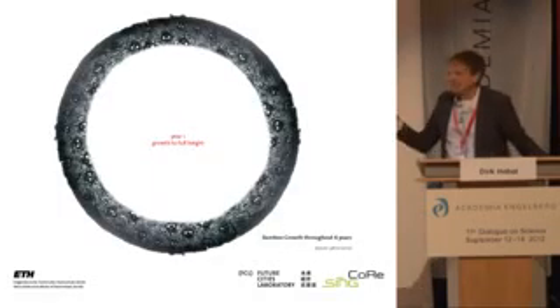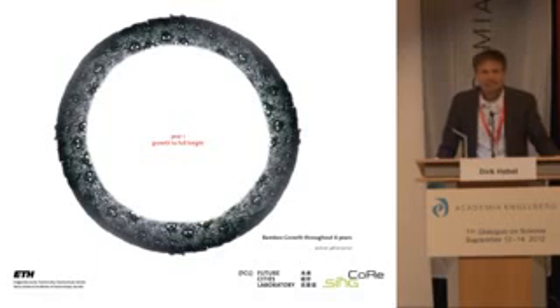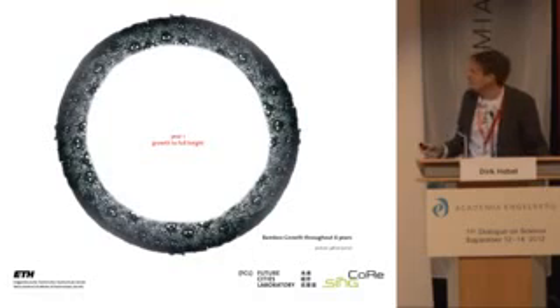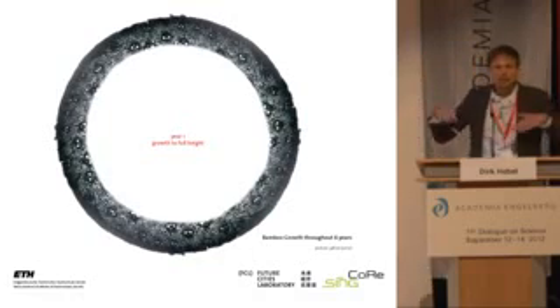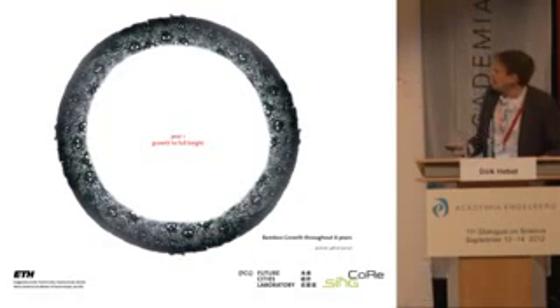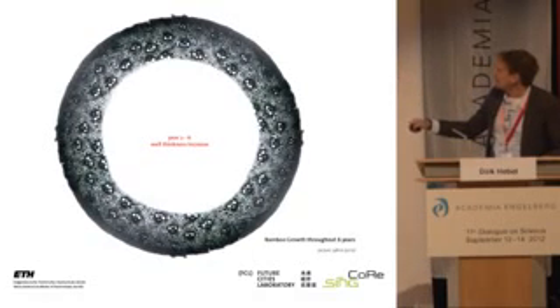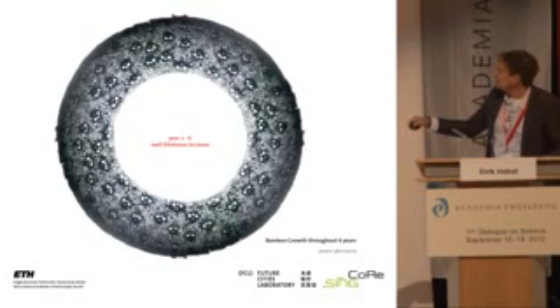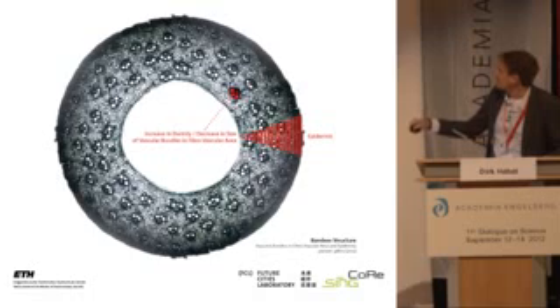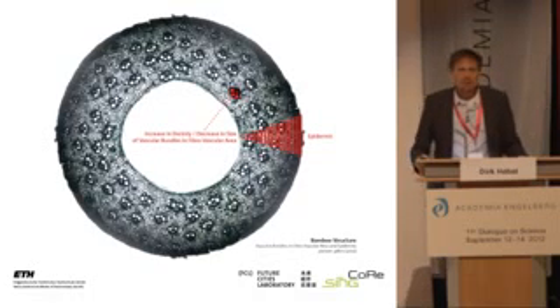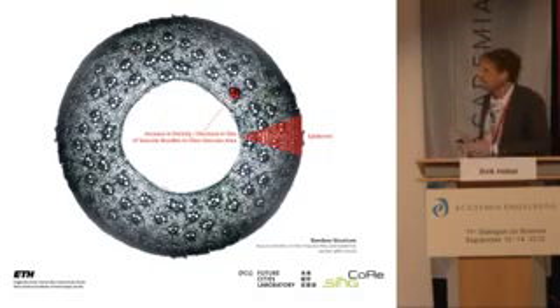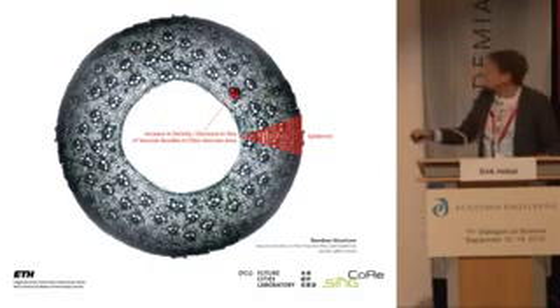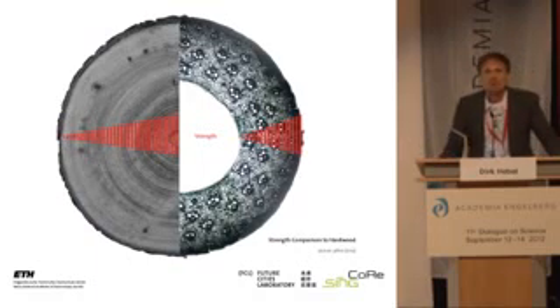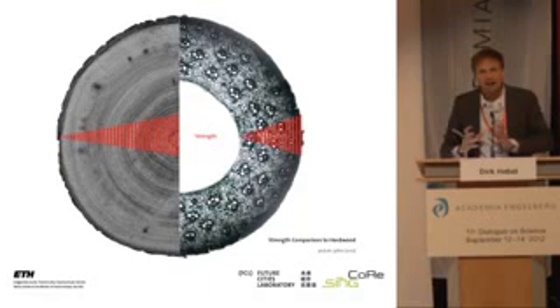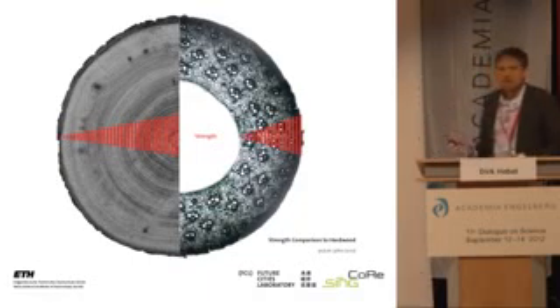But also, you see that bamboo is a very, very interesting material in the fact that it is not growing from inside out, as we usually know it from our trees here in the European context, but bamboo is growing from the outside in. So you see here a stem of bamboo in the first year of its growth, the second year of its growth, and the wall thickness is more or less increasing to the inside. The strongest parts of the bamboo are also on the outside, on the so-called skin or epidermis. You see it here, which is in complete contrast to what we usually know from the timber industry, where the hardest or the strongest part of a timber is found in the center.